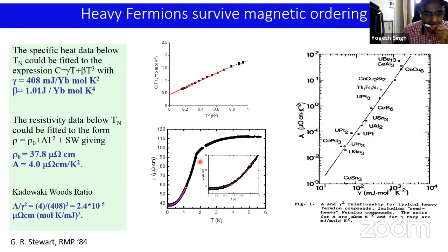And again, the resistivity at low temperatures can be fitted by a T squared, where the A coefficient again is quite large. So for heavy fermions, one takes a Kadowaki-Woods ratio, which is just a ratio of the A coefficient divided by the square of the Sommerfeld coefficient. And this is a universal number for most heavy fermions. So let us see where ytterbium falls on this chart. Here is ytterbium, and these are all the other heavy fermions which were known previously. And we see that ytterbium falls reasonably close to this Kadowaki-Woods universal ratio, confirming that this is a heavy fermion compound.